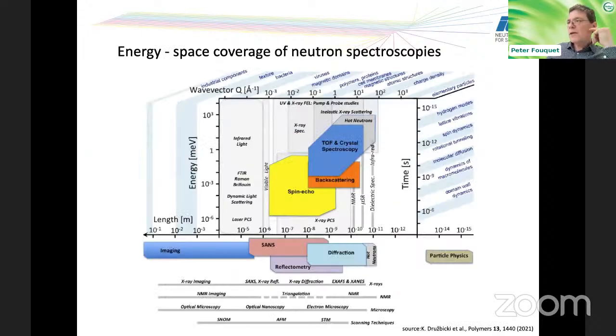Huge ranges of length scales. So you see the length scale displayed on the bottom line here. So that goes from the micrometer upwards, from the nanometer upwards. And then you have the time scales that are between microsecond and picosecond and below. And this can all be covered at the same time. And the nice thing about neutron scattering is that you get the spatial information and the spectroscopic information, the time information, at the same time.